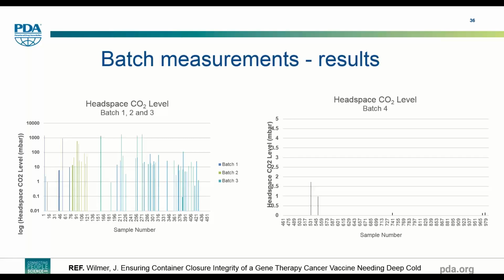And so the point that I wanted to make here is that it is possible to develop a CCI method for GMP product. And in fact, the requirement here was that the product would not have a temperature excursion of more than 60 seconds. So the CCI test had to be done within that 60 seconds, but it was possible to do that and generate the data, giving insight into the quality of the batches.